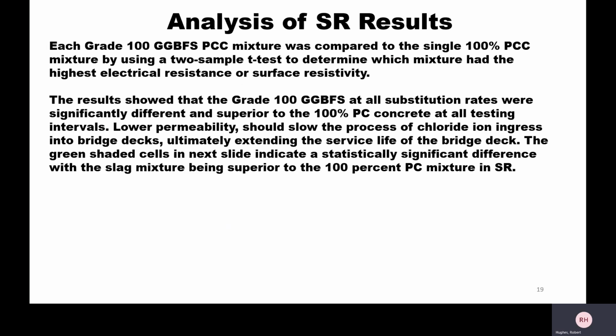Statistical analysis of SR. Each grade 100 GGBFS concrete mix was compared to the control mix, 100% PC, using a two-sample t-test to determine which mixture had the highest electrical resistance, or surface resistivity. The results showed that the grade 100 GGBFS at all substitution rates were significantly different and superior to the control 100% PC at all testing intervals. So lower permeability should slow the process of chloride ion ingress into bridge decks, which will therefore extend the service life of the bridge deck.